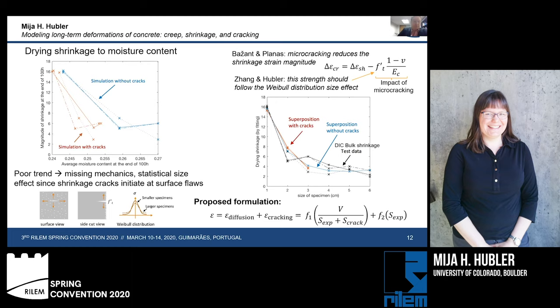Moving on, we'd like to now relate the drying shrinkage to this moisture content. However, if I create the plot here on the left, looking at the magnitude of the shrinkage at a certain time as a function of the moisture content, we find that there is a poor trend relating these two. There's something missing. And what is missing here is the mechanics.